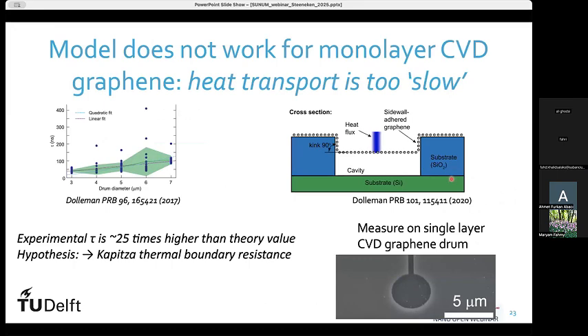However, when we tried this for graphene, we found that this model that we had didn't work well. The time constants we found, so the time it took to heat up graphene, was 25 times larger than what we expected from our model. So we started investigating this more, and we had the hypothesis that this was caused by a thermal resistance that exists at the boundary of the graphene. The graphene is not perfectly flat when you put it on such a membrane, but by the van der Waals forces, it adheres to the substrate, which bends it a little bit at the edge.